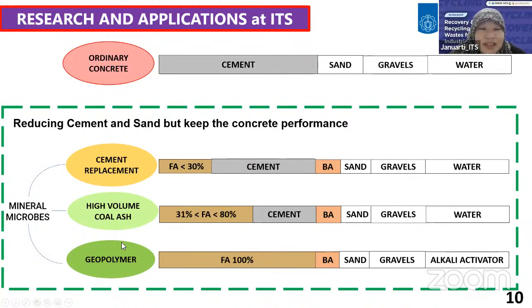And the last one, the very famous one, is geopolymer. We don't need any Portland cement. We just use fly ash 100% to replace cement. And we also use bottom ash to replace sand, and we use gravel as usual, but we replace water with an alkali activator.